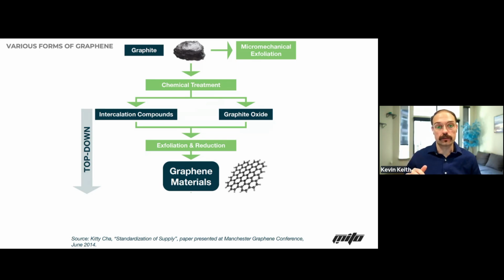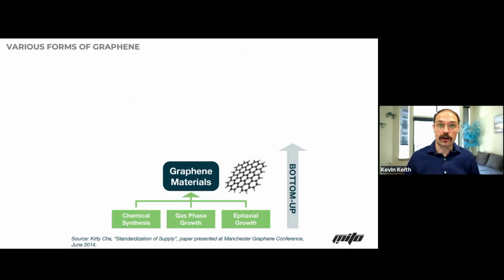Then you have a chemical treatment method where it splits off into two different methods. You have graphene oxide, where you're putting it through a chemical bath and you're oxidizing the graphene and blowing those layers apart. Another one is that you can pair mechanical and chemical exfoliation to get those layers apart. You can still grind it up. It's in a wet process, but you can still more effectively control your layer count. And then beyond that, you can exfoliate it, reduce it, do some other treatment methods to that, and then you get these graphene materials.